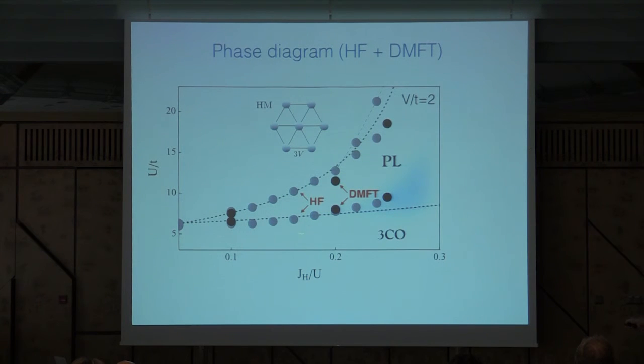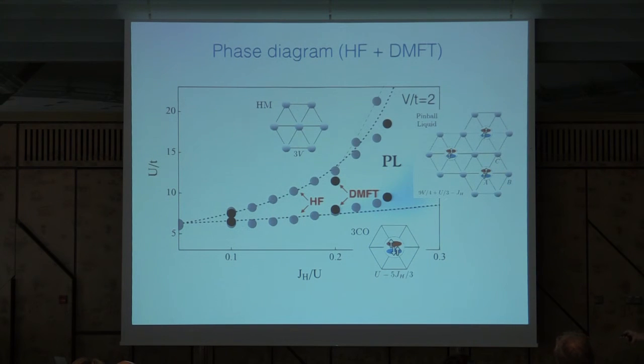On the other end of the phase diagram, down here, the cost in U is small. So what we want to do is put as many electrons as we can on the same site. We will put 3 here, and this site and this site will be empty. This is full charge order. But there is this intermediate region where you get exactly what I was showing before: 2 electrons on this site, and then the remaining electrons act as a liquid flowing in these interstitials. As you increase the Hund's coupling, this region broadens and it stabilizes this pinball.